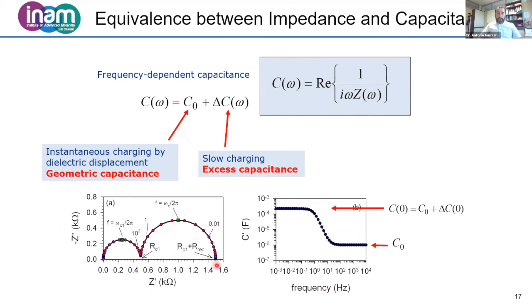And two well-resolved arcs lead to two plateaus in the capacitance frequency plot. This high frequency arc will be observed at high frequencies. So this is the geometrical capacitance, related to the dielectric relaxation processes of the semiconducting material. And this capacitance we observe at low frequencies is called excess capacitance, and is related to slow charging of your semiconductor. I will explain later the meaning of this capacitance in perovskite solar cells.